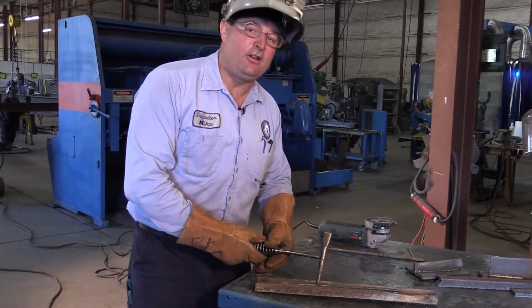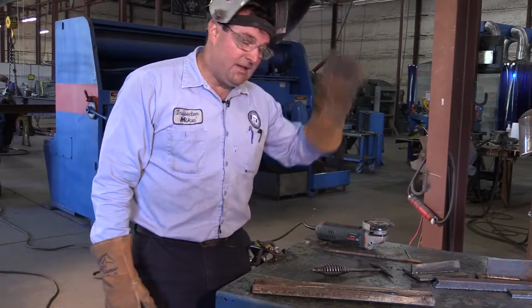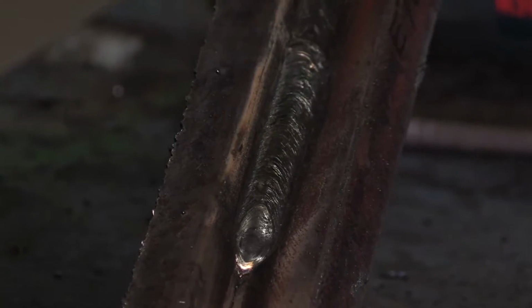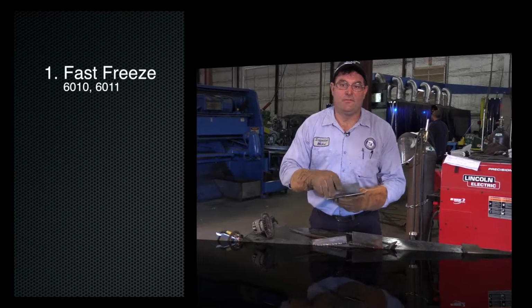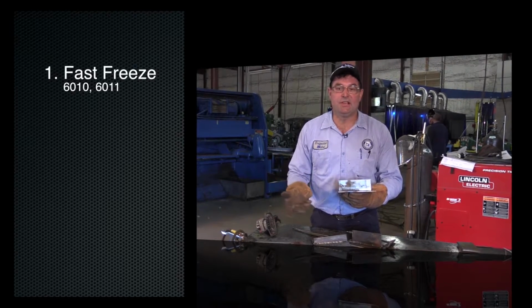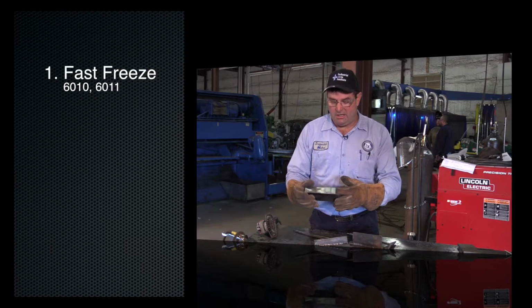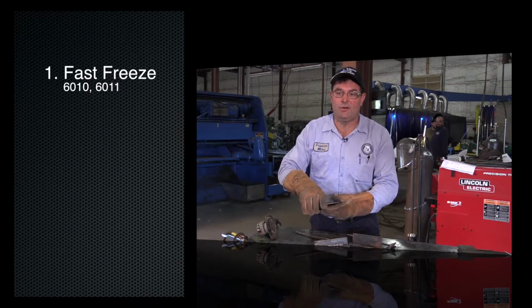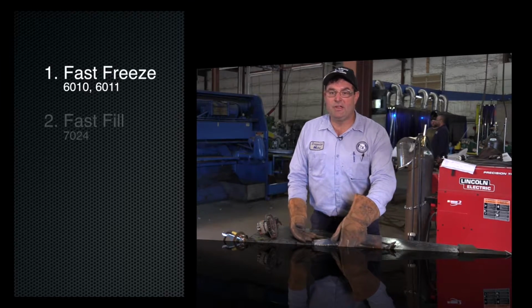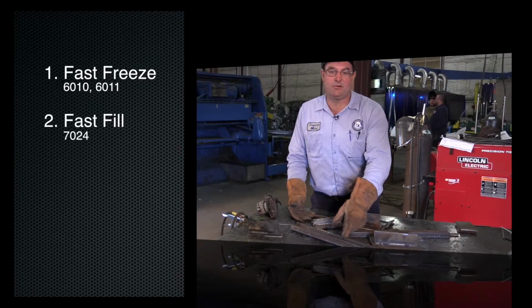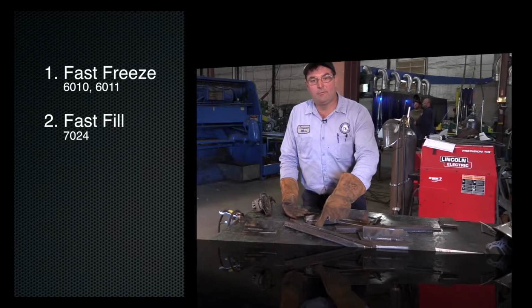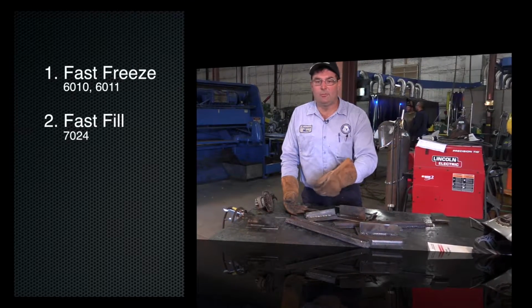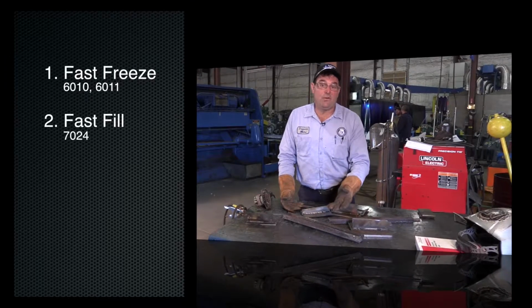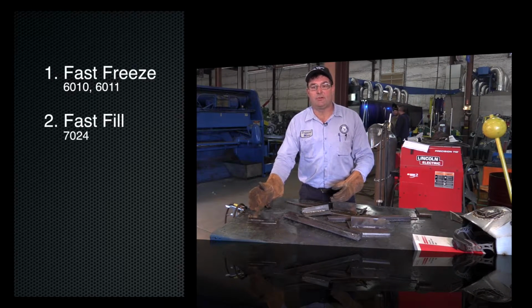See, nice bead appearance, easy to run. If you had something that required a lot of deposit, don't need low hydrogen, flat position only, 7024, hard to beat it. Fast fill. So far, we went over fast freeze electrode, 6010, 6011, that type where I have the whipping action. Welding dirty stuff, thin stuff, whatever. And then on the other end of the spectrum, we have the fast fill, 7024 type electrode, 7028 if you need low hydrogen, where I can put a lot of deposit down, pretty bead, no manipulating, but I can only weld flat with it. Two totally opposite type electrodes, okay?